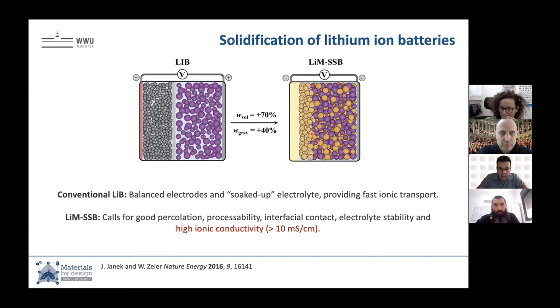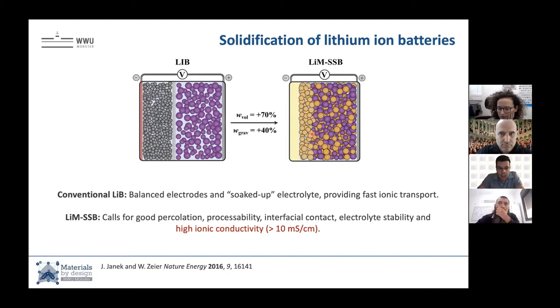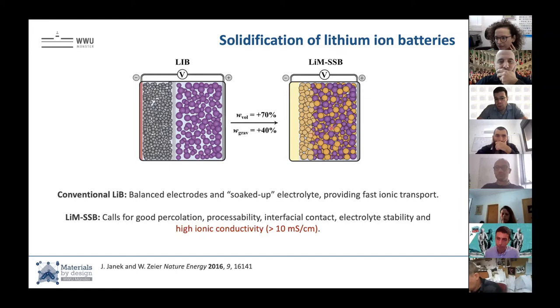The hope is that we should get higher energy density and better charging. Companies, especially last week, have announced quite a major push there. But to achieve this you need good percolation, good interfacial contact, electrolyte stability, and in the end you still need electrolytes with conductivities on the order of 10 millisiemens and above, mostly because of percolation and tortuosity issues in solid state batteries.